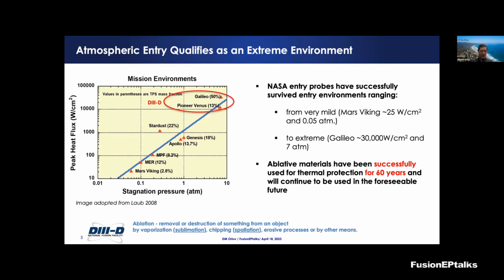The atmospheric entries are usually qualified as an extreme environment, and NASA used the probes successfully in different regimes. Some of those regimes were mild on the peak heat fluxes, like the Mars Viking here. Some of them were extreme on the peak heat fluxes, like Galileo or Pioneer Venus. And what I want to show on this figure on the left is, if you think about the peak heat fluxes, the D3D tokamak can give us heat fluxes that are comparable to the most extreme ones that the probes and spacecraft experienced when entering Venus or Jupiter.